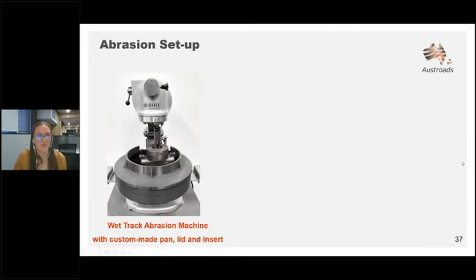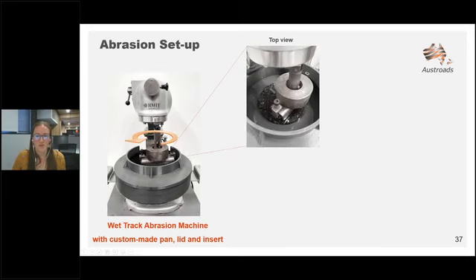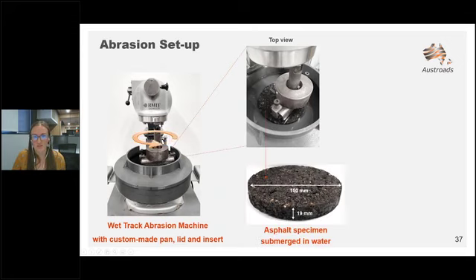In order to answer this question, we developed a new procedure, and we used a new testing machine called the wet track abrasion machine. This abrasion machine works by using a rotating head, as you can see here, which is in contact with an asphalt sample, and this is used to simulate abrasion as it would occur on the roads with the cars. This is just a top view of the machine. So you can see the asphalt sample that is maintained here in the pan, and it is covered with water.